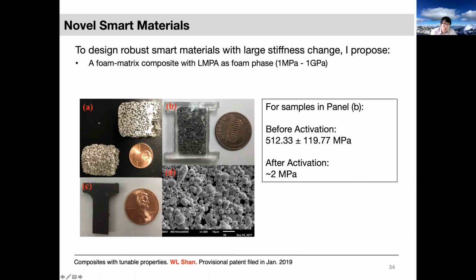But when you activate this whole thing, you literally have a PDMS containing liquid alloy inside, and this material will be very soft. And as you can imagine, we can do hundreds of times difference in stiffness, and this has been verified by experiments. But it is also very robust.